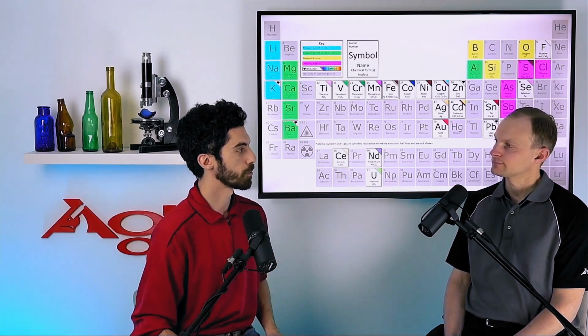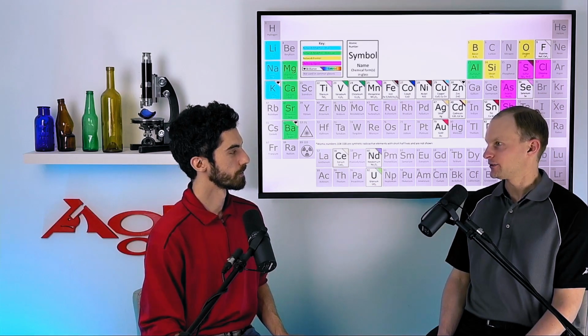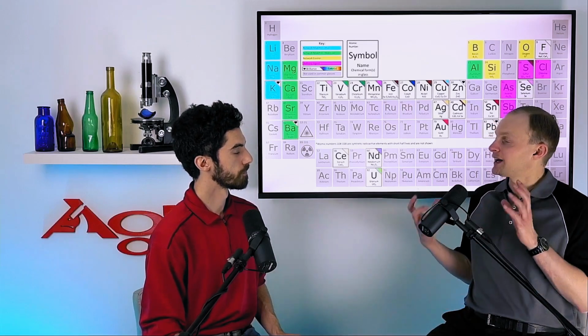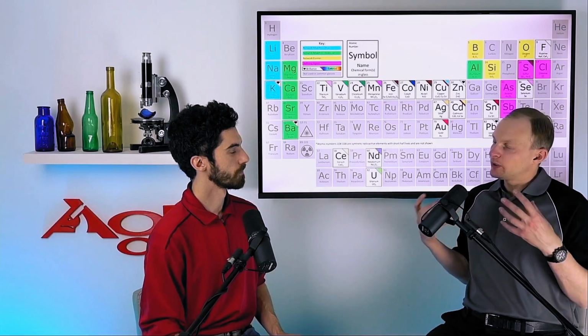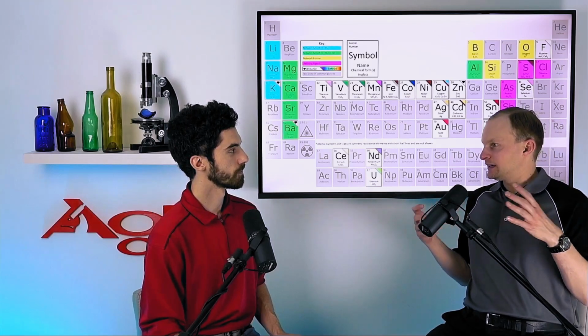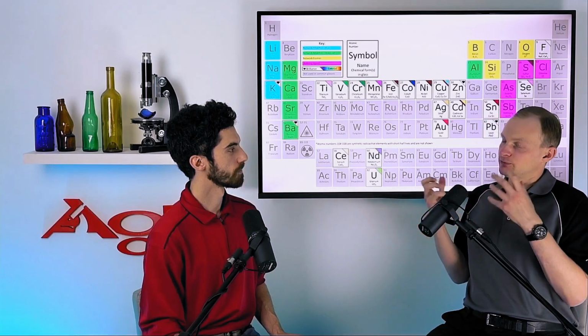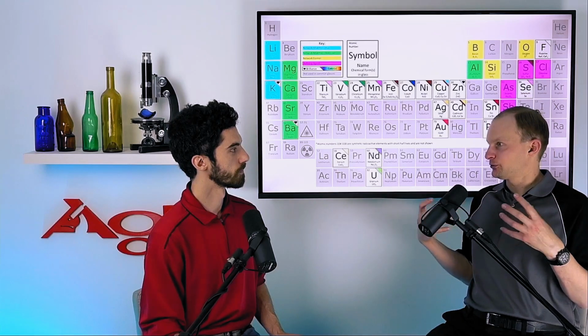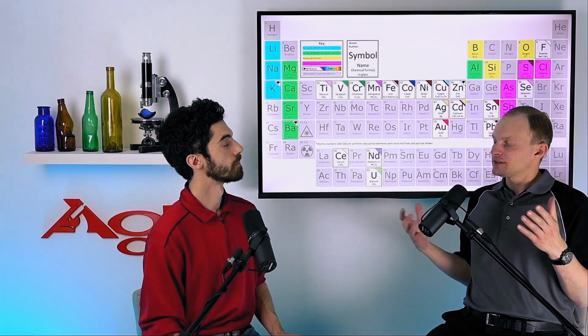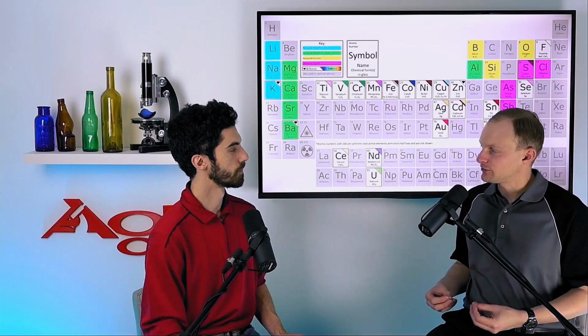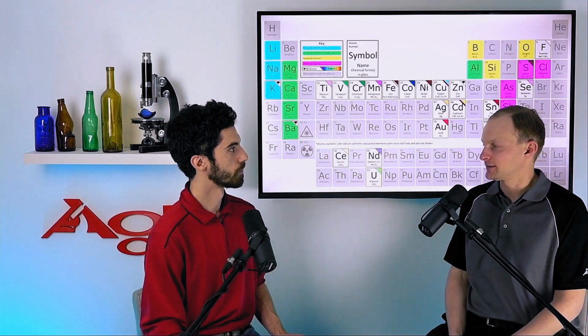What allows glass to be endlessly recyclable, unlike, say, paper or plastic? Okay, so there's a lot of things, but the real main factor is that if we ignore all the other stuff, glass is made up of primarily SiO2 and all sorts of oxides of different elements. When we are melting glass back into whatever form we want, making it molten and then into another shape, it's staying in that compound, in the oxide form. So we're not changing its chemical structure, we're just changing its physical state. Same thing with aluminum cans. That's the element aluminum. We're not changing its actual chemical structure, we're just changing its physical state. We're melting it and then we're making it into something again.